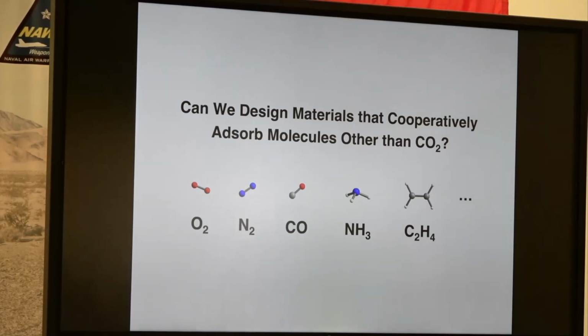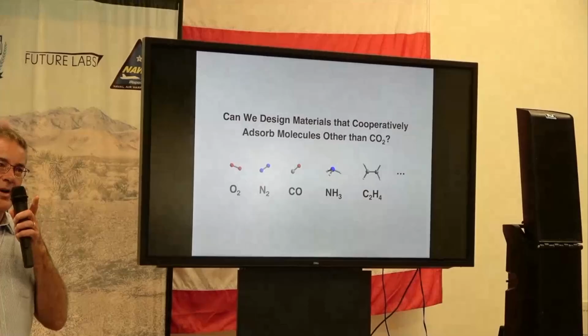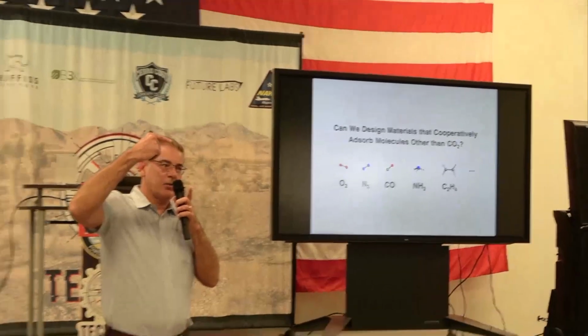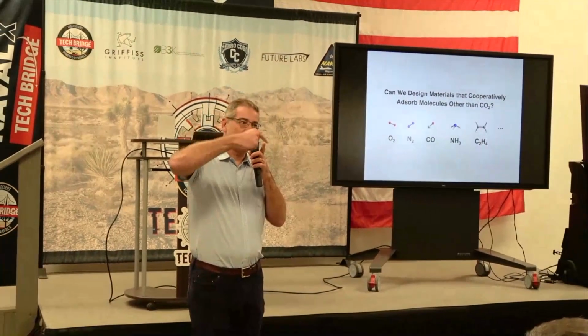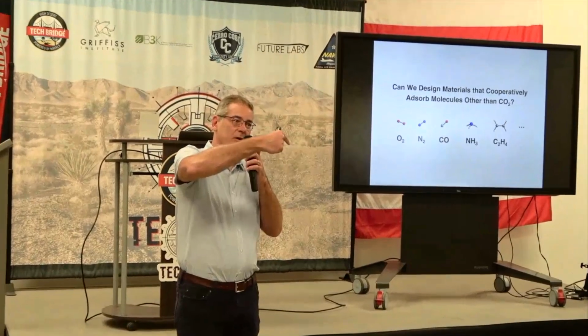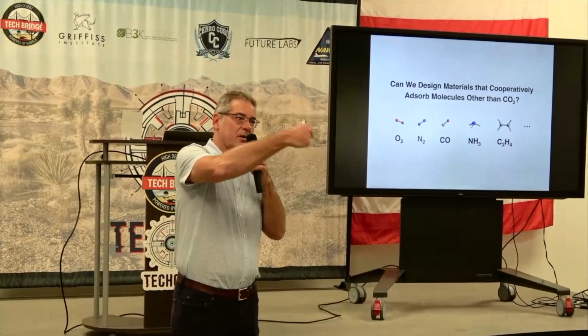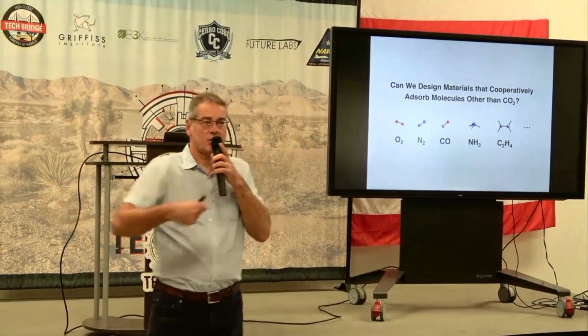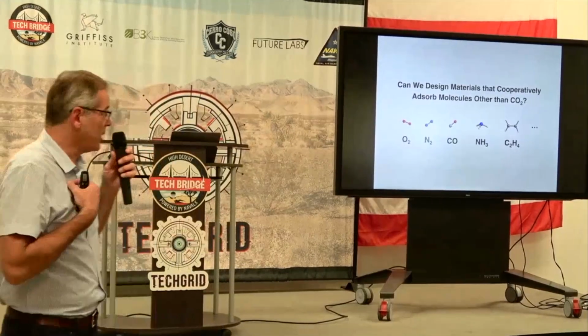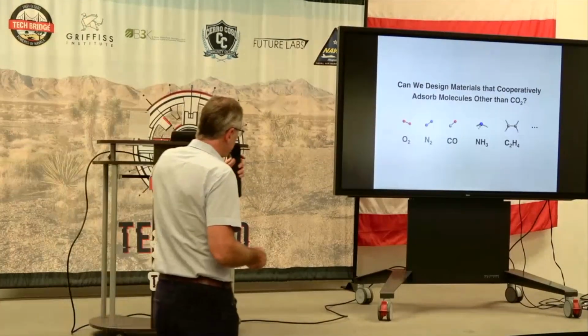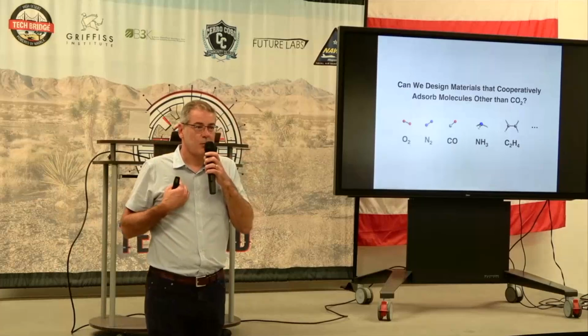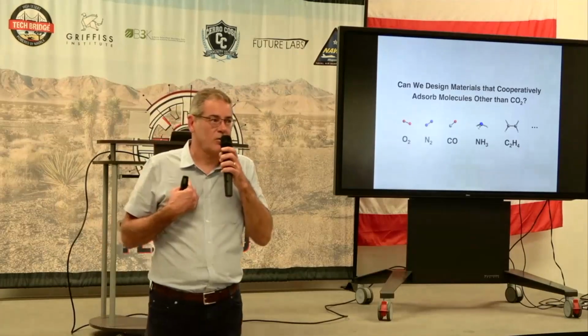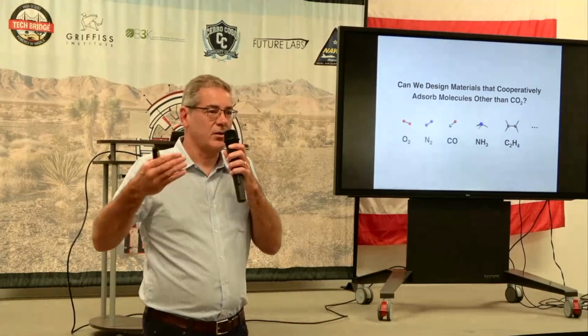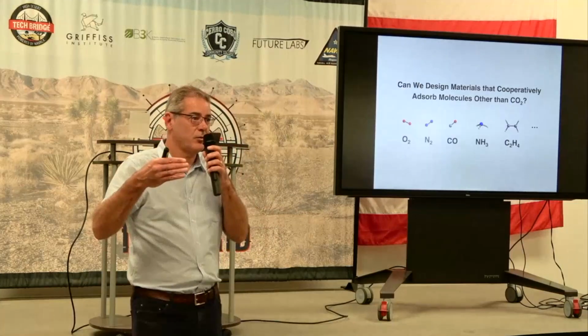This is a design challenge, a puzzle. How do you get one of these molecules to be selective in binding to the surface? And for cooperativity, you want it to be such that when one molecule binds, it lowers the energy for another to bind and another, and you want that to propagate through the structure. Right, so these are all chemical puzzles. Nature can do oxygen and hemoglobin. Nobody knows how to do cooperative O2 adsorption at high density. If you do that, you'll change the way O2 is produced from air.